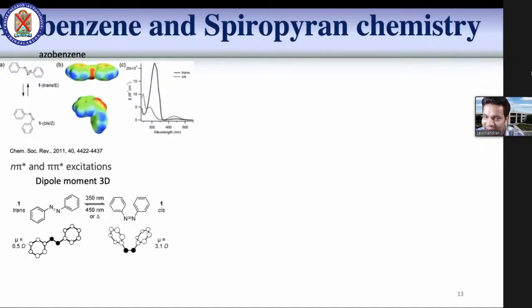Azobenzene is a simple organic molecule. You have two aromatic rings with an N double bond N. When used with the appropriate wavelength, this azobenzene undergoes photoisomerization from trans to cis configuration, which is n-pi* and pi-pi* excitation. The trans state is a stable one, the cis is an unstable one. Importantly, the dipole moment changes, and this process is reversible.